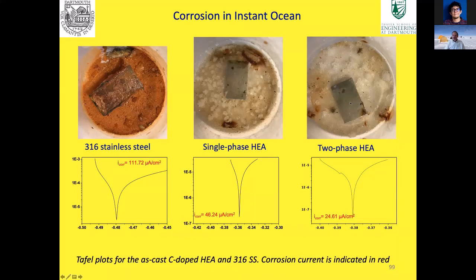So the top images here are some very crude experiments that I did, where we just took stainless steel, the single-phase high-entropy alloy, and the two-phase high-entropy alloy with chromium, and we put them in a solution of instant ocean. What instant ocean is, if you've got a fish tank with fish from the ocean, you can buy this stuff, put it into water, and it basically replicates the chemistry of the ocean.